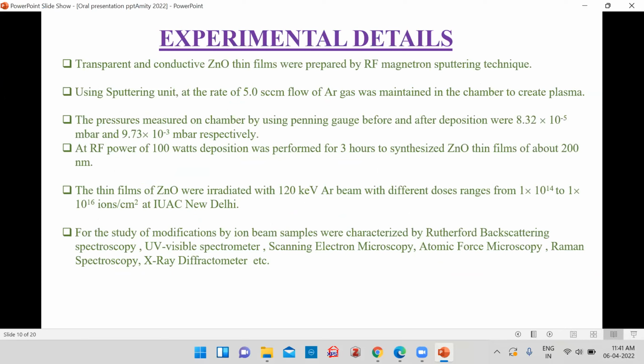Then we irradiate the thin films of ZnO with a 120 keV argon beam at different doses ranging from 1 into 10 to the power 14 ions per centimeter squared to 1 into 10 to the power 16 ions per centimeter squared at IUAC New Delhi. Then we study the modification in the ion beam irradiated samples by using characterization techniques like Rutherford backscattering, UV visible spectroscopy, scanning electron microscopy, atomic force microscopy, Raman, and XRD.